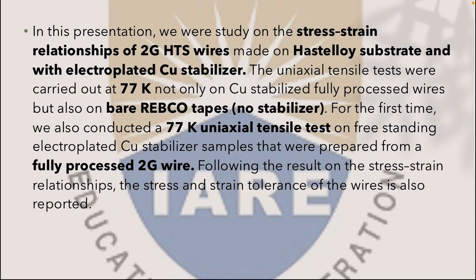The uniaxial tensile strength tests were carried out at 77 Kelvin, not only on copper stabilized fully processed wire but also on bare REBCO tapes, with no stabilization. For the first time, we also conducted a 77 K uniaxial tensile stress test on a freestanding electroplated copper stabilizer sample that was prepared from a fully processed 2G wire. Following the results on the stress strain relationship, the stress and strain tolerance of the wire is also reported.